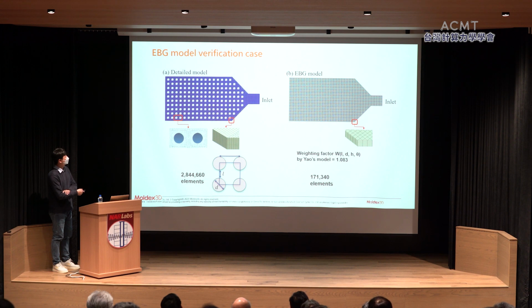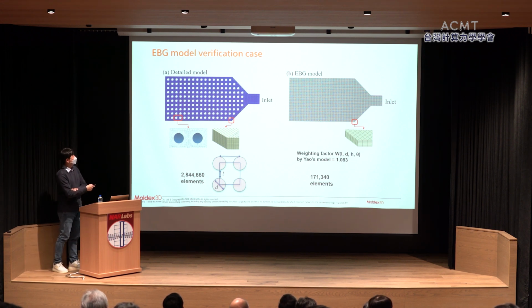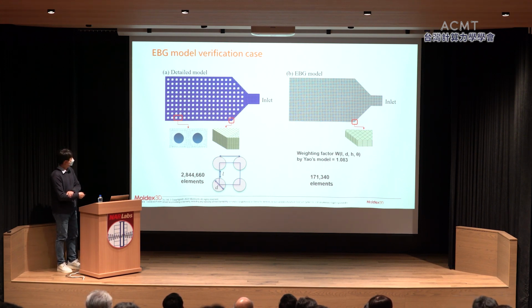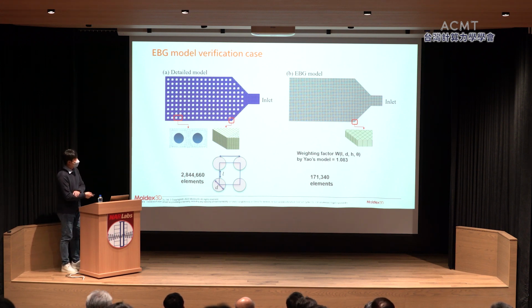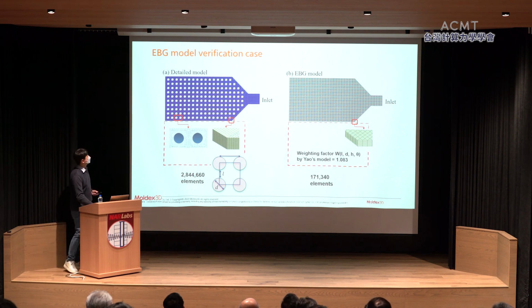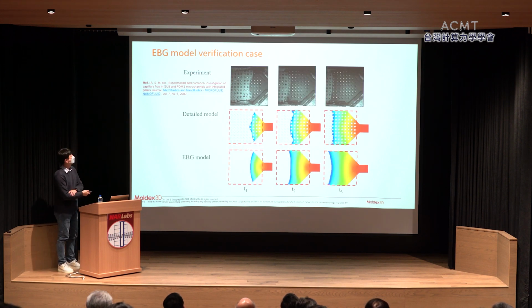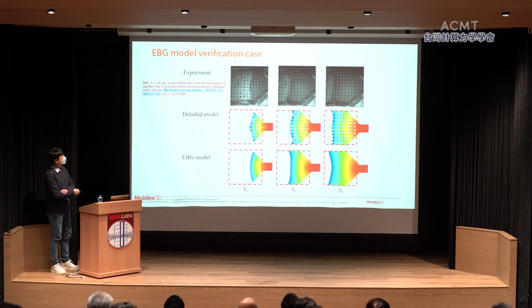And here is a verification by a very simple case. You can see here we use a very high resolution mesh to meet the boundary. We call it the detail model. And this is the equivalent model. The detail model needs 2.8 million elements, and here we only need 171,340 elements. By comparing the experimental data, the detail model and the equivalent model, you can see we have very good agreement among them.